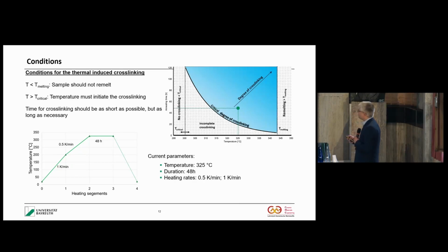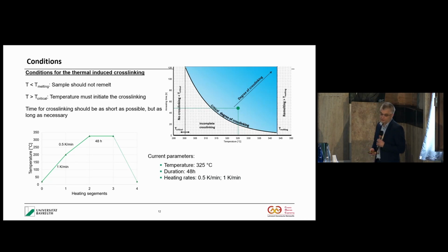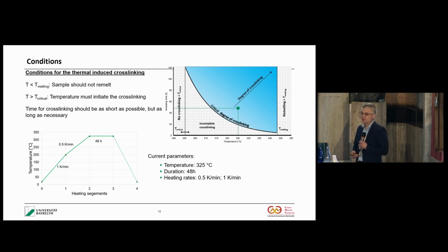And so you have a processing window. We recently explored this processing window quite intensively. You see the current parameters, I think, were published recently. It's allowed 48 hours, so it's quite a long time, so the disadvantage of long processing times is still present. There are other ways for the cross-linking, but this is the easiest one. If you use, for example, acids, it can also be done. So cross-linking is essential, and shortening the processing time still has to be investigated.